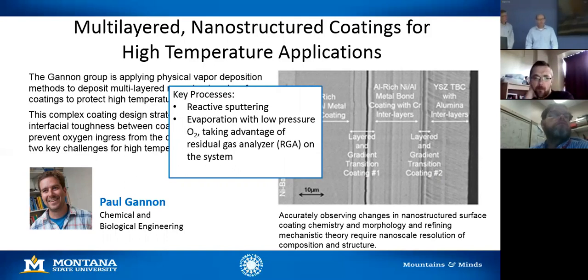We ended up using an evaporation tool for that, with a residual gas analyzer so we could actively control partial pressures of oxygen. By maintaining that, we would maintain the oxide characteristics of this YSZ material.